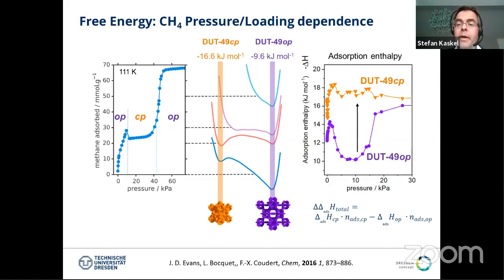And due to the great cooperation with Philippe Llewellyn and Paul Jacomi in Marseille, we were also able to measure experimentally these adsorption enthalpies for the OP and for the CP phase. And we find an average adsorption enthalpy here in this relevant range, which is about 10 kilojoule per mole for the OP phase and about 17 kilojoule per mole for the CP phase. So much, much higher in magnitude. And basically it means that due to the energetic preference of the methane molecules for the CP phase, they contract the structure at intermediate loading, and only at high loading, basically due to the higher capacity of the OP phase, the total amount multiplied with the adsorption enthalpy then leads to the reopening. So that's the mechanism behind the contraction.